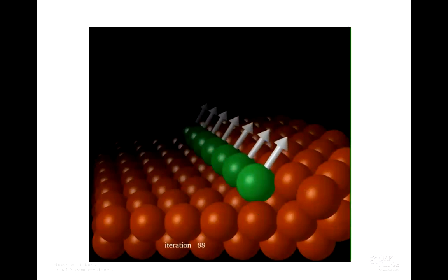And in this movie, you see these 2 different time scales. It started out with the atoms aligned in the plane, and as we start the simulation, they very fast align parallel to each other. That's the energy scale and the time scale of the exchange interaction. And then they very slowly find the ground state direction. And this is the 1,000 times slower process that's associated with the relativistic effects.